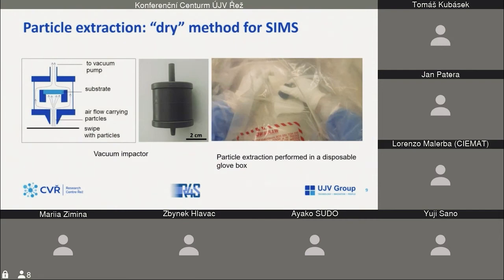In the rightmost image, you can see the particle extraction, which is made inside a disposable glove box. It is very important to prevent so-called cross-contamination of our samples. This means contamination from the extraction from the previous swipe.